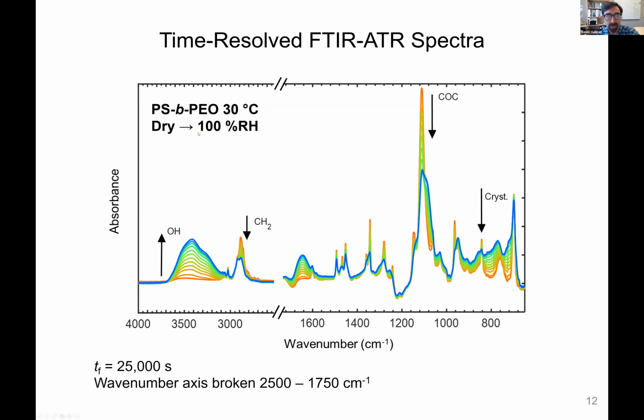And as time goes by, this dry polymer has been exposed to 100% humidity. These water peaks increase with time. Each of these spectra is at a different point in time through the course of the experiment.